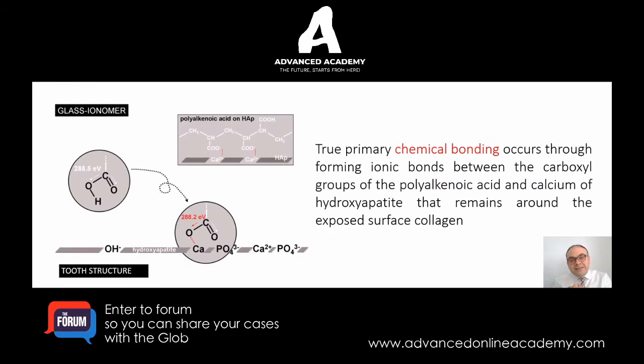Glass ionomer has a true chemical bond to the tooth structure. That is something to take into consideration: there's a chemical interaction between the hydroxyapatite in the dentin and the carboxyl groups of the polyalkenoic acid. And so the true chemical bond happens between the glass ionomer material and the tooth structure.